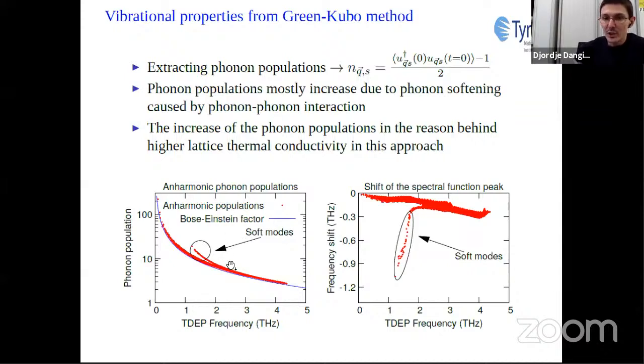Why do phonon populations increase? We understand that from the plot of the frequency shifts between the fitted frequency and the assumed harmonic frequency in the Boltzmann transport equation approach. And we can see that the phonon softening due to the phonon-phonon interaction causes anharmonic phonon populations to increase, which increases the overall lattice thermal conductivity.